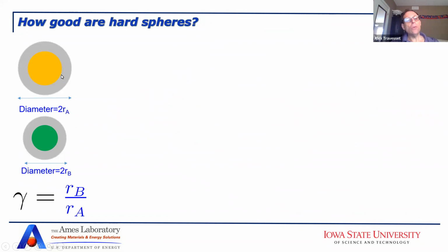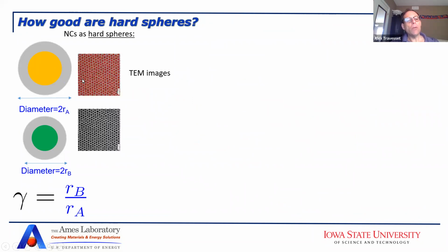Well, the way to relate it to the experiment is that what people typically do is put these nanoparticles on a 2-dimensional triangular lattice, and then they measure each nanoparticle separately. You measure the lattice constant, and the lattice constant for this single-component 2-dimensional triangular lattice gives you an idea of the equivalent hard sphere diameter or hard sphere radius for this sphere.